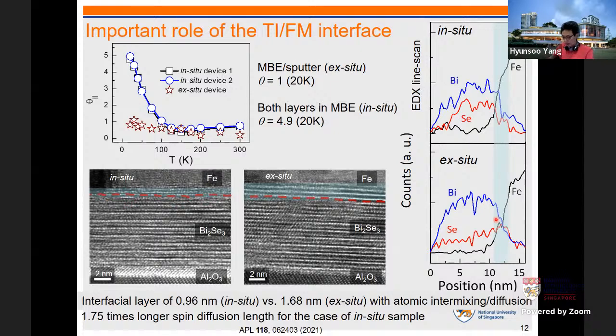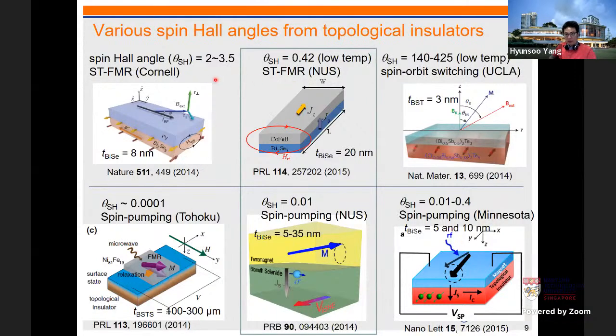Number 1 is the thicknesses. Okay, so if you now go back to here, we can see Cornell used 8 nanometer. Initially, we used 35 nanometer. Tohoku used 300 micrometer, and UCLA used 3 nanometer. So you can see if they use a thinner film, in general, they can see a much larger effect. But if they use very thick films, they end up with very small values. The other one is temperature measurement. Some groups reported extremely low temperature, UCLA, and also my group, but later we also see those effects at room temperature and so on. And also a different group used a different chamber, so the interface quality could be quite different.